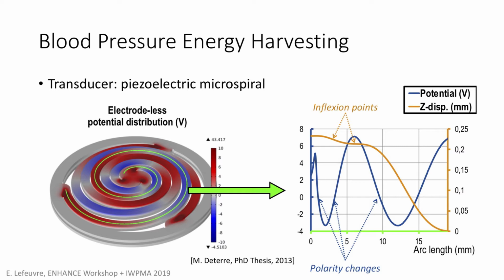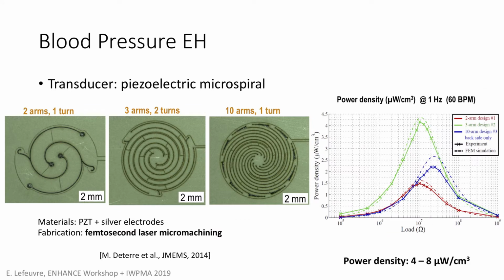So we tried to go to analytical modeling, but it was just a nightmare. So we said, okay, that's the way it is. We will run a lot of simulations and see what works better. So that's what we did, and we came to these three designs. They are 5 millimeter in total diameter, so they are compatible with the diameter of the capsule. The first one is only 1 turn per arm and 2 arms, and then we tried 2 turns, 3 arms, and 10 arms, 10 turns, 1 turn, sorry.